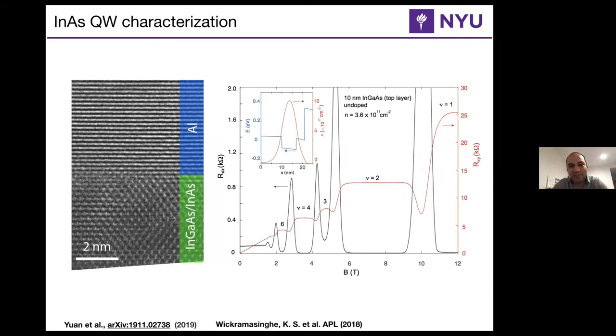So once you have that system, you obviously want to know what the aluminum is doing and what the semiconductor is doing. And now you can only access the semiconductor by removing the aluminum. That usually involves an etch. There are very nice selective processes, actually. It's industry-based, but any process has its own side effects, right? So given that already included, we actually can get mobilities up to 45,000 centimeters squared per volt-second. This is longitudinal and Hall data up to 12 Tesla on one of the samples.